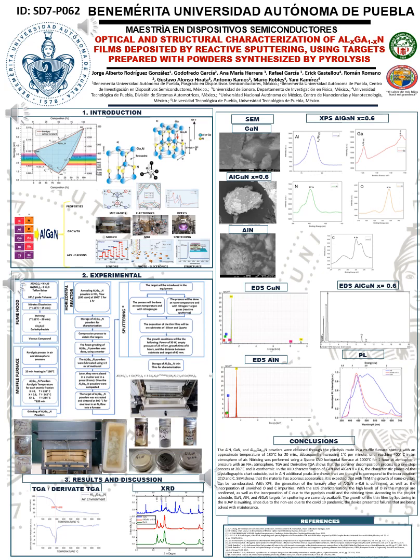TGA and derivative TGA show that the polymer decomposition process is a one-step process at 286 degrees Celsius and is exothermic. In the XRD characterization of GaN and AlGaN, X equals 0.6, the characteristic planes of the crystallographic chart coincide, but in AlN additional peaks are shown that are thought to correspond to the incorporation of oxygen and carbon. SEM shows that the material has a porous appearance. It is expected that with TEM the growth of nanocrystals can be corroborated.